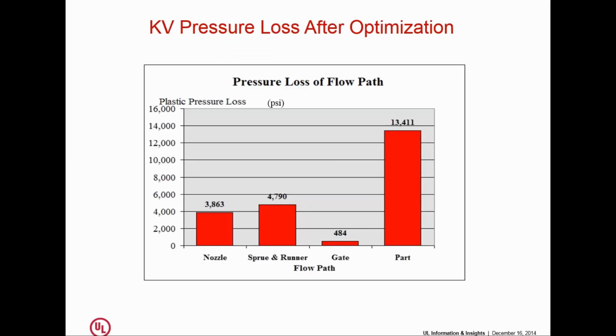Now we can document pressure losses all the way through a process, from the nozzle all the way through to the end of the flow path of the part. There's a technique, which we can't go into today, called a pressure drop study. This is the result of that pressure drop study. It shows where pressure is being lost. So you lose a little bit of pressure going through the nozzle, you lose a little more going through your sprue and runner, you lose a very small amount going through your gate, and then you lose a fair amount just in the act of filling the cavity, driving the material from the beginning of the cavity to the end of the cavity.